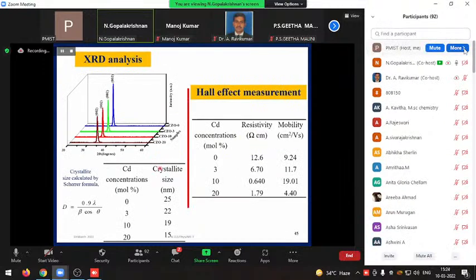So first part, this is the cadmium doped zinc oxide film. We took XRD and confirmed that the film is single crystalline with 002 preferential orientation, with the hexagonal wurtzite structure. Then we measure the crystal size using the Debye-Scherrer formula for different doping concentrations. Also we measure the Hall effect, resistivity and mobility, and then we characterize the film.